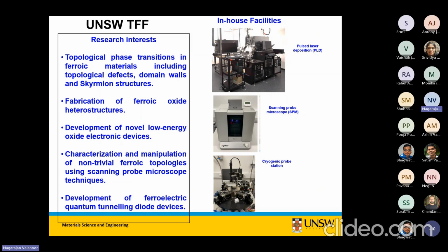We just installed a cryogenic probe station about 6 months ago. We don't have much data to show for that, but I know it works because we got some PE loops at about 100 Kelvin, and they're nice and square and sharp, and they're believable. So hopefully in the near future, we will start to throw some data on that as well. I won't talk to you about the quantum tunneling diode devices that we've also developed because it's too much time and too much talking, and it's not in bismuth ferrite. But we are trying to develop that in bismuth ferrite now as well.